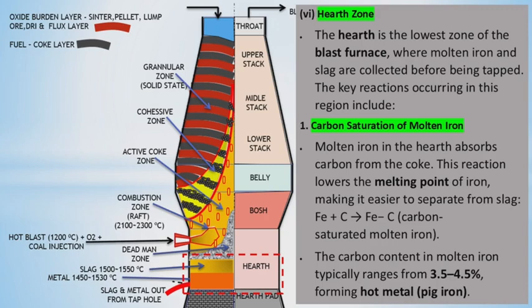The key reactions occurring in this region include carbon saturation of molten iron. Molten iron in the hearth absorbs carbon from the coke. This reaction lowers the melting point of iron, making it easier to separate from slag. Fe + C = Fe-C, carbon-saturated molten iron. The carbon content in molten iron typically ranges from 3.5 to 4.5%, forming hot metal, pig iron.